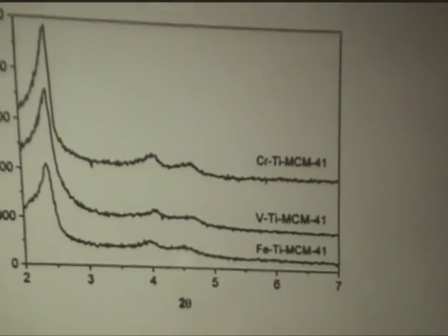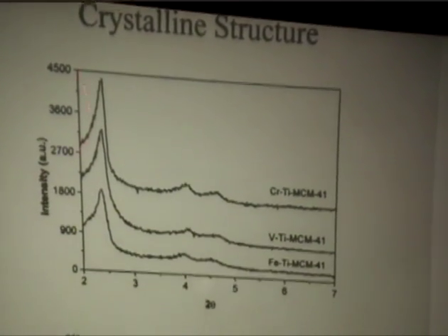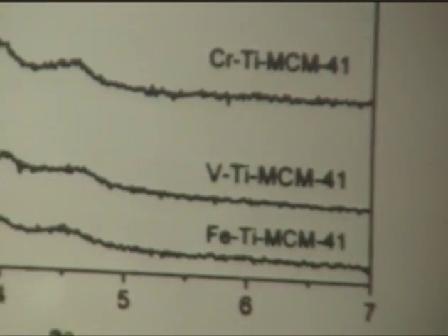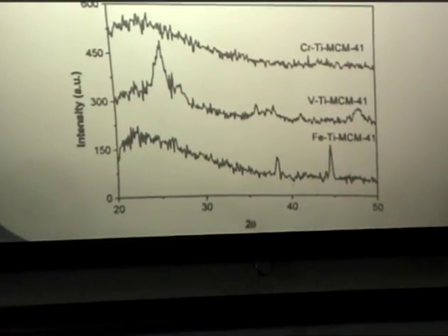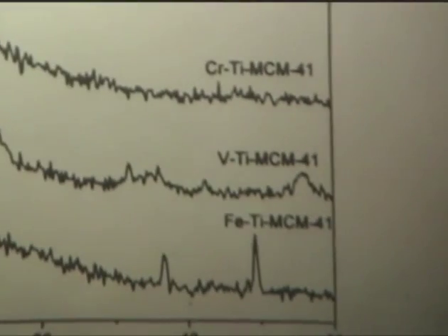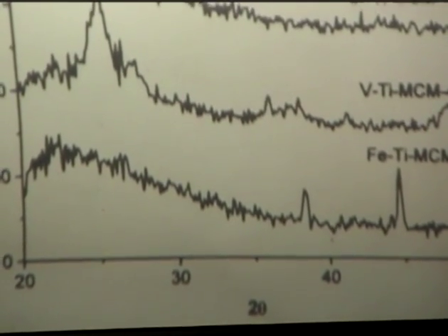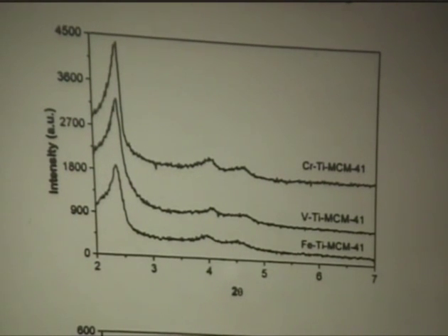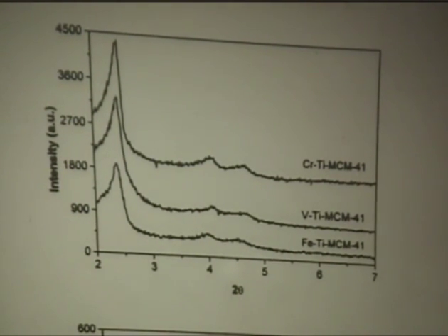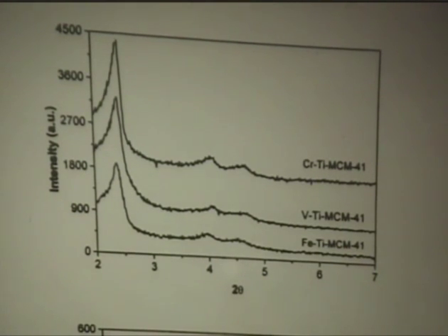Let's look at the crystalline structure as reported by XRD. We observe a large peak at about 2.5 degrees two-theta, and two other peaks also observed for any MCM41-based material. However, the absolute values of these peaks are lower than reported for standard siliceous MCM, apparently due to the inclusion of foreign transition metal ions into the framework. In the range of 20 to 30 degrees, recorded to detect any well-formed crystals of transition metal oxides, we essentially observe that there are none.